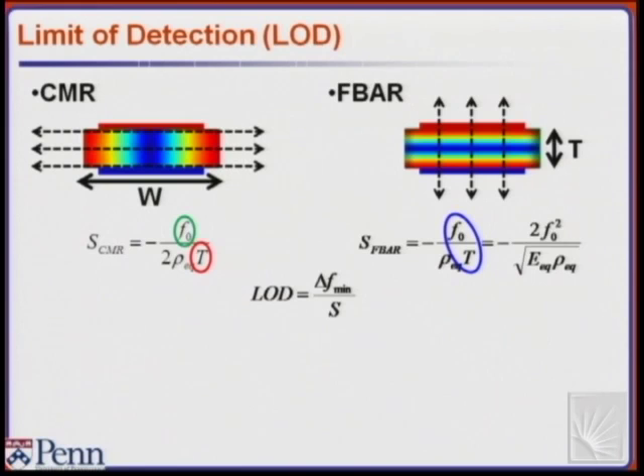We're monitoring, and maybe I did not clarify that for the audience, we're using the resonator as a balance, substantially. Adding mass to the resonator will change the resonance frequency. The resonance frequency of a mechanical element is always the square root of K over M, so if you're adding mass, you're changing the frequency. That's the principle of operation. So what you're monitoring is frequency shifts, and you want to detect the minimum possible frequency shift. The minimum detectable frequency shift is generally proportional to the center frequency divided by Q.